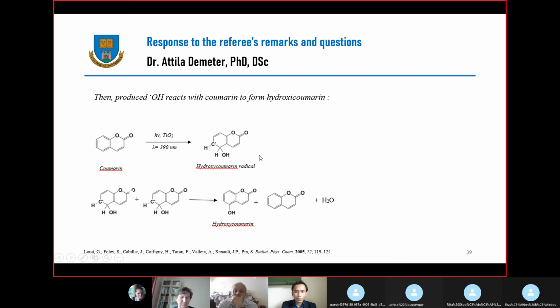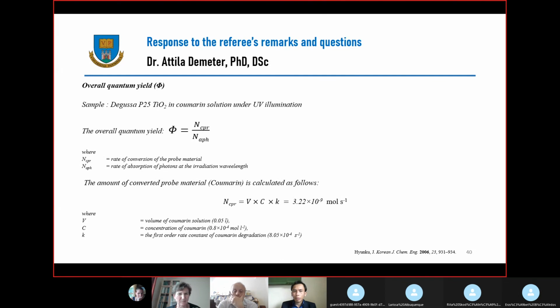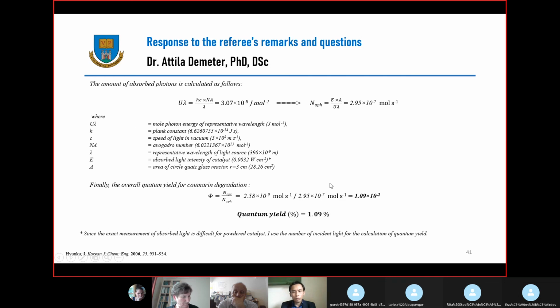The first step produces the hydroxycoumarin radical, like here. So this hydroxycoumarin radical reacts with each other, producing the hydroxycoumarin and the coumarin compound. So this is probably the very primary quantum yield of this reaction. And we also calculate the overall quantum yield with this we obtained from the previous literature. So this is the calculation of the quantum yield for the Degussa under UV illumination, and then we got a value around 1.1 percent of the total.